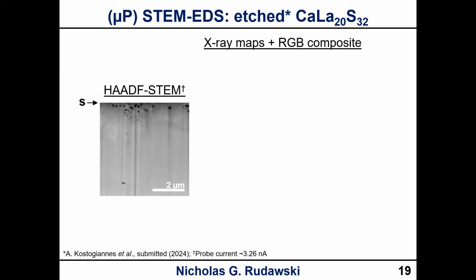So here's an example of this. This is microprobe-STEM EDS, so this isn't just for imaging. You can do this analytically as well, and this is one of the areas where it really shines, in my opinion. If you're doing any kind of analytical work, chemical mapping, EDS, EELS, on the micro scale, you really have no need to do this in nanoprobe. There's really no reason why you would want to use anything but microprobe.